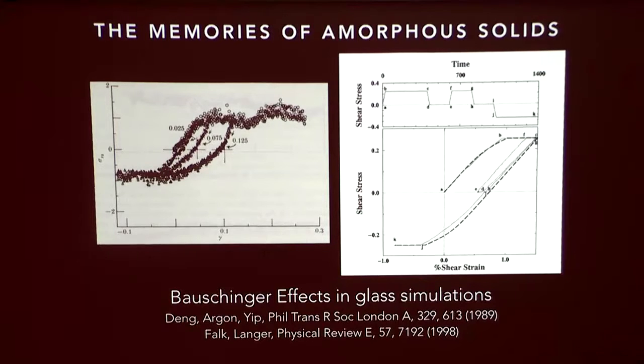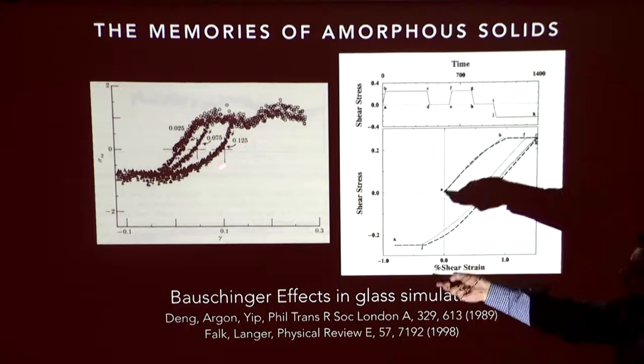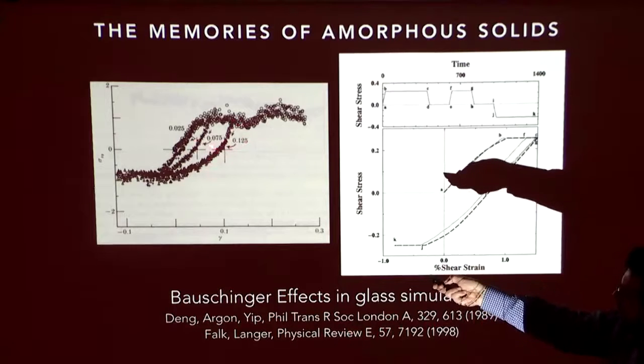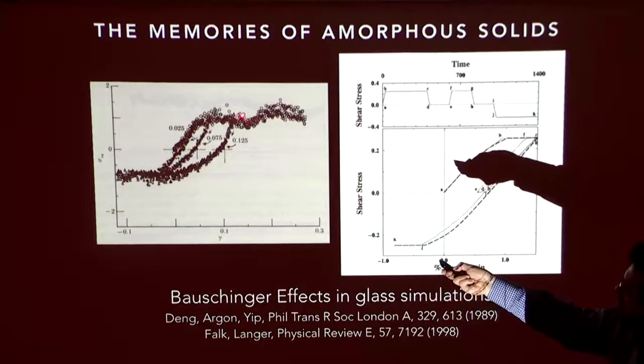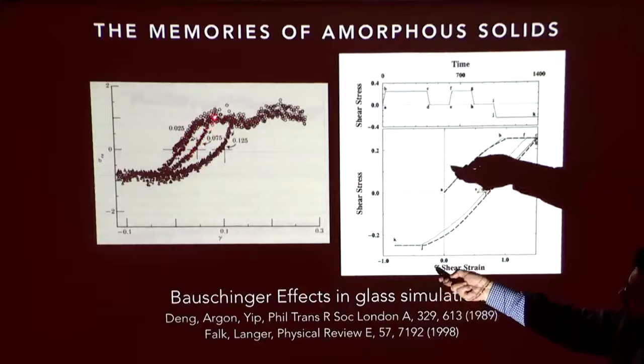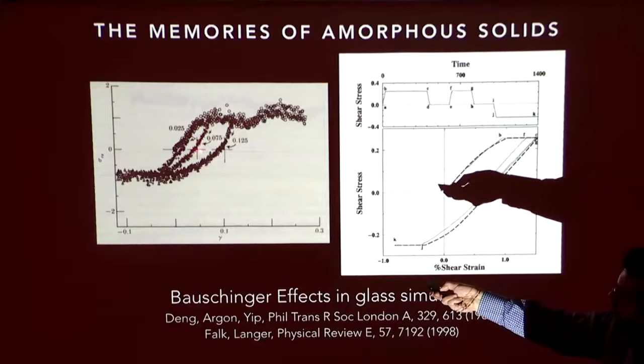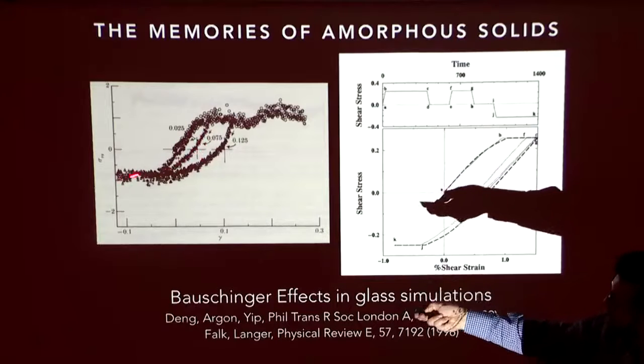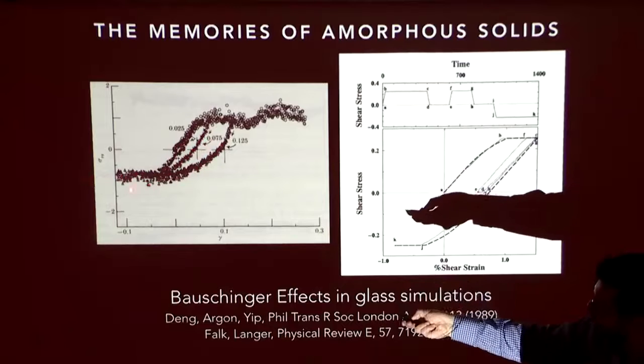This was also observed in simulations. I think the first sighting I know of it was by Sid Yip and Ali Argon in 1989. This was the data from that paper - you see they load the system, then unload it. Upon unloading, it's fairly linear, but when you load it in the reverse direction from zero, it's considerably softer.